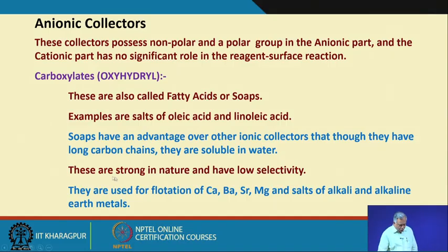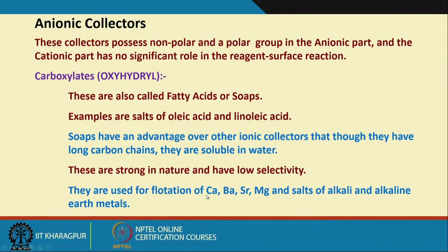These are basically strong in nature and have low selectivity. This gives you a very stable bonding, but they have lesser selectivity. Where are they used? They are used for flotation of calcium, barium, strontium, magnesium, and salts of alkali and alkaline earth metals.